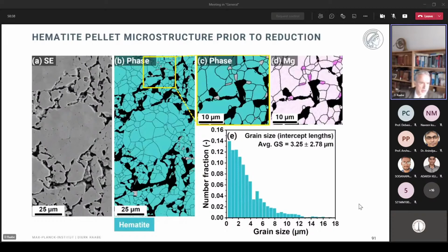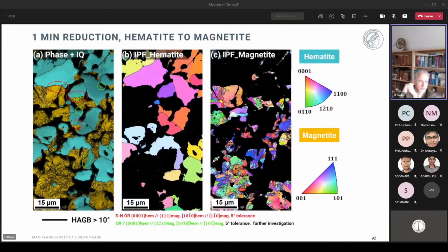Here you have a hematite pellet, a commercial one, as I said. You run it in a secondary electron mode or look at the phase contrast with EBSD. Then you can nicely see this hierarchical structure. We have on the inside a polycrystalline substance with many grain boundaries and a lot of porosity around it that comes, of course, from the sintering. And this porosity is very important for reaction kinetics.